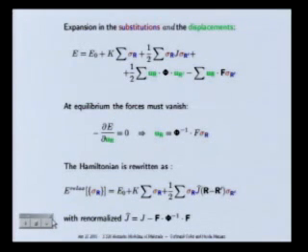So what we have here is the physical embodiment of the degrees of freedom. The energy is expanded up to the second order, but then we also apply an equilibrium condition. That is, the force on the ions for a given configuration sigma must be zero, so the first order derivative of the energy with displacement, that is the force, must be zero. And if you apply that to this and you work the algebra, you really obtain, for a given set of configurational variables, what are the displacements away from equilibrium that are induced by these configurational variables.